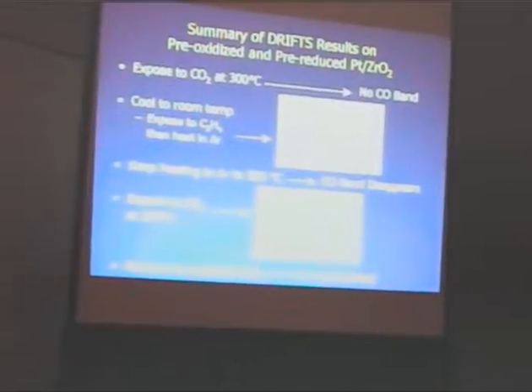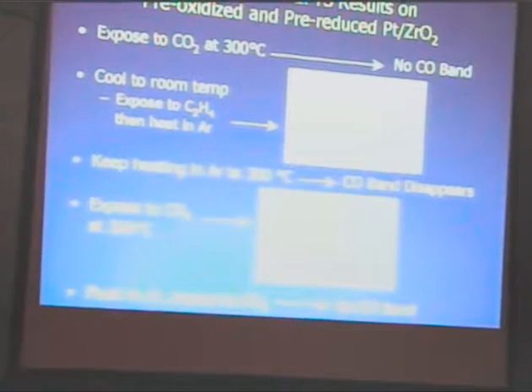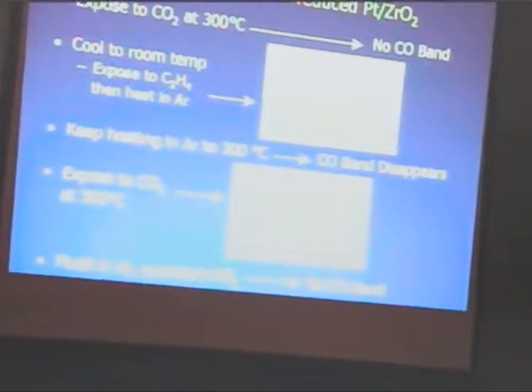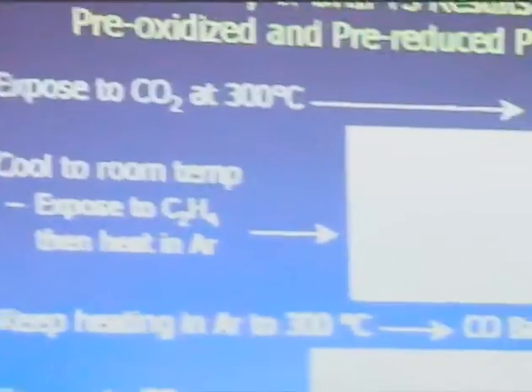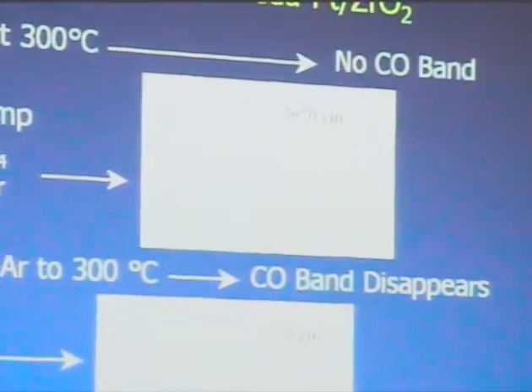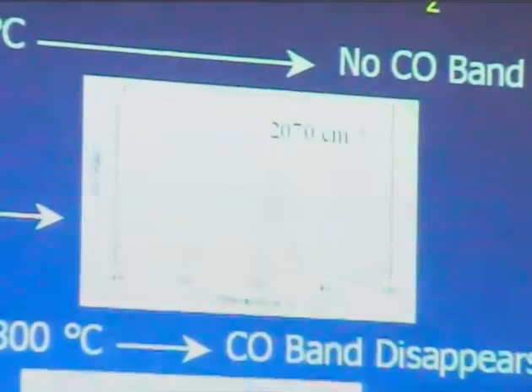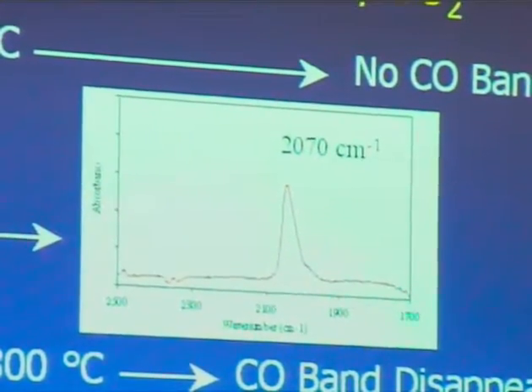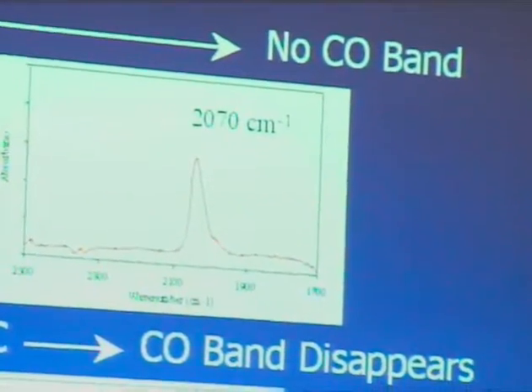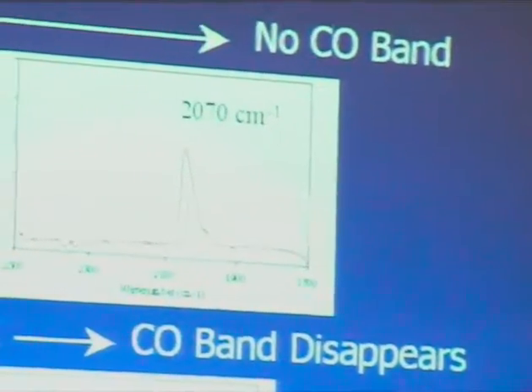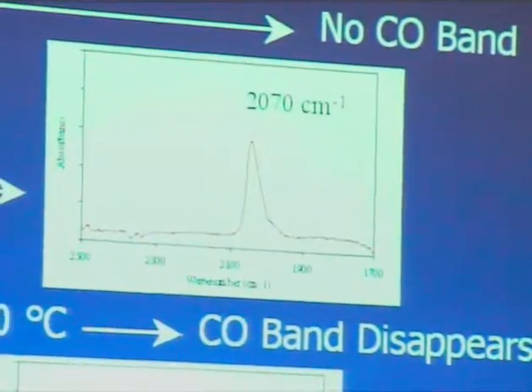We cooled this material down to room temperature, and then we exposed it to C2H4 to try and impose some surface contaminants or some hydrocarbon species on the surface. We then heated that material up in argon, and when we heated that material up, we now see the appearance of the linearly adsorbed CO at 2070 on the metal. What's happening here is that the hydrocarbon is decomposing. When the hydrocarbon decomposes, it reduces the zirconium support, forms CO, and that CO shows up as linearly adsorbed CO on the metal. If we continue to heat in argon to 300 degrees C, the CO band disappears.